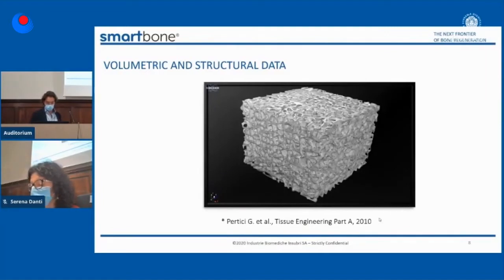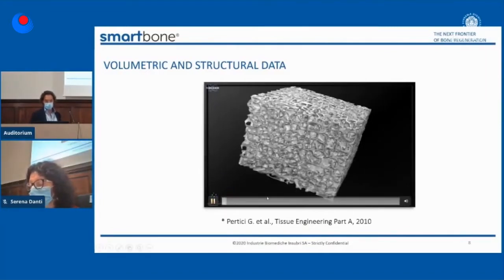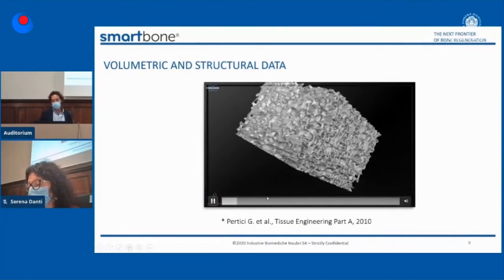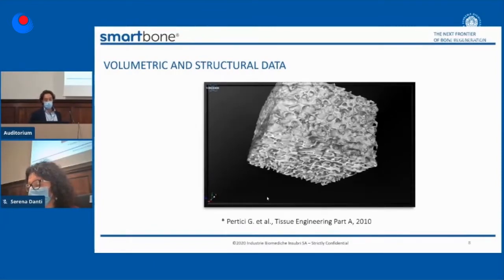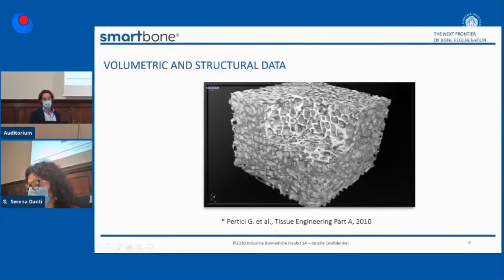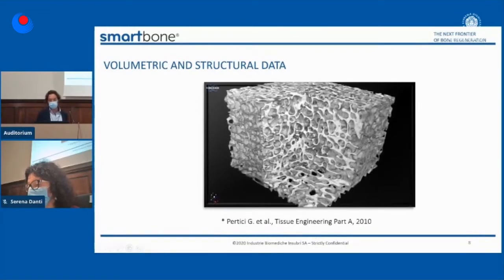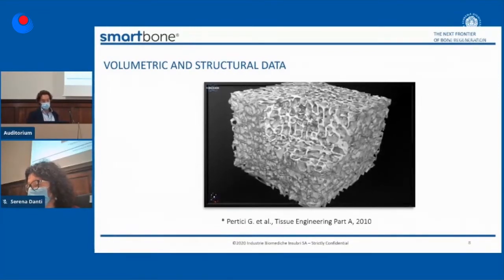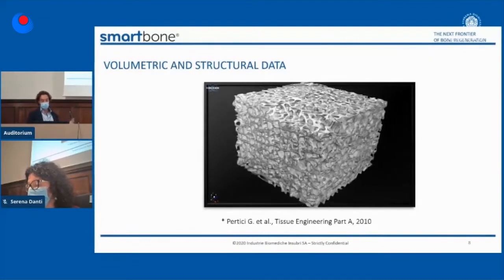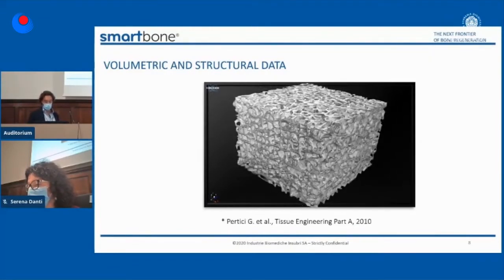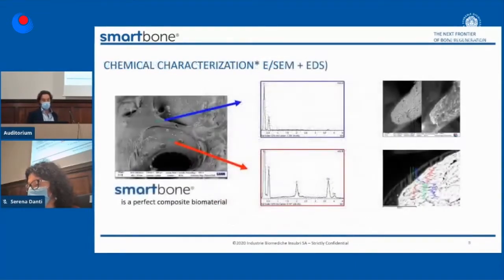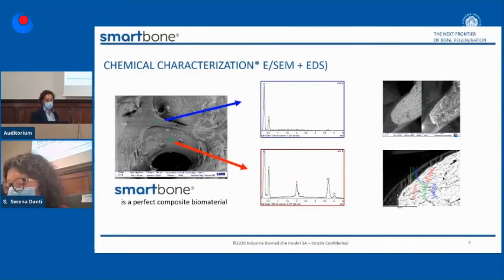Here we can see that after this treatment, we still maintain an open and interconnected porosity. That is a key point for regeneration. The blood has to arrive everywhere inside the graft, and obviously has to exchange nutrients and waste. If you look at a cut of this bone graft, you can see that our treatment is a kind of coating that we put onto the surface of the trabeculae, the inner surface of the material.